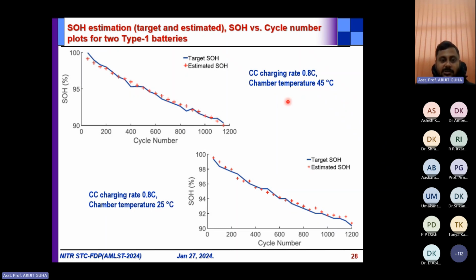And this corresponds to type 1 batteries. In one case, the charging current was 0.8 C, and the chamber temperature was controlled in a thermal chamber, which is enclosed. If you program it to maintain 45 degree, it will maintain 45 degree throughout. And once you change the level to 25 degree, it will maintain that throughout. No fluctuation will happen. Under those two scenarios, it has been observed that the target SOH and estimated SOH are pretty close. You can see here in this case and in this case also.